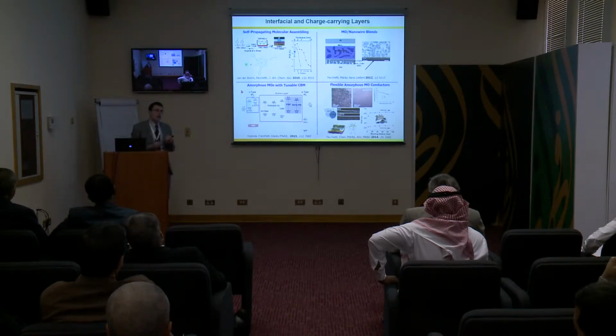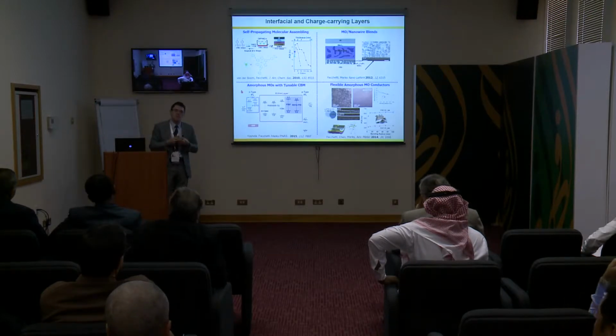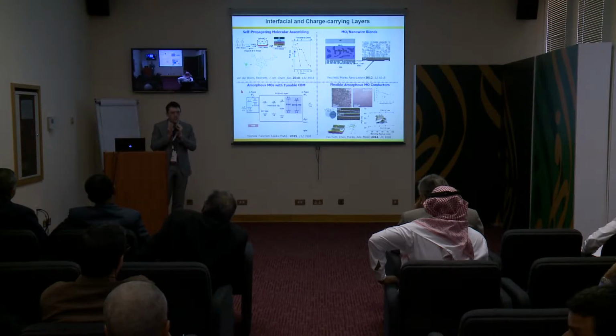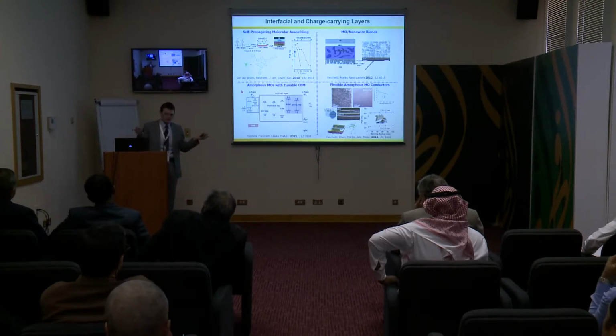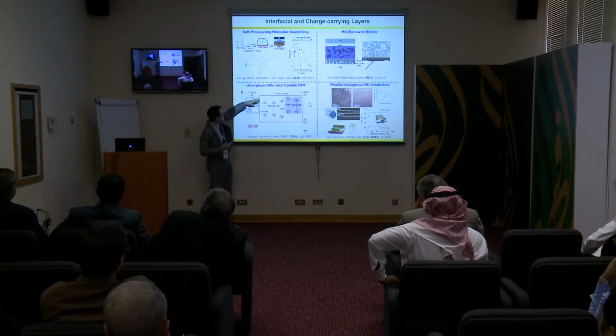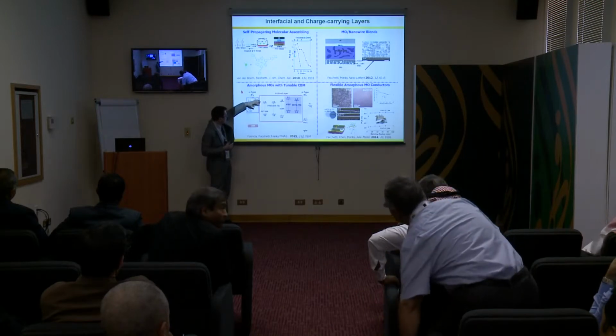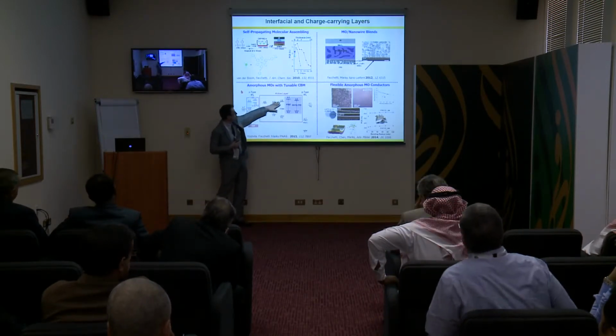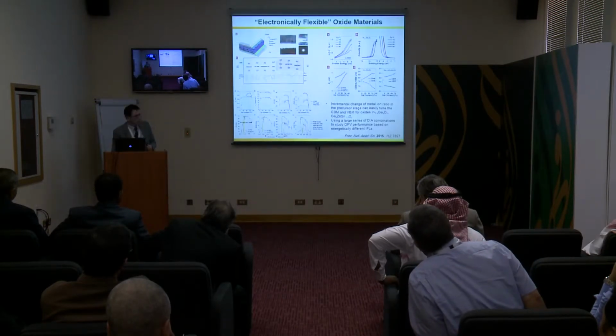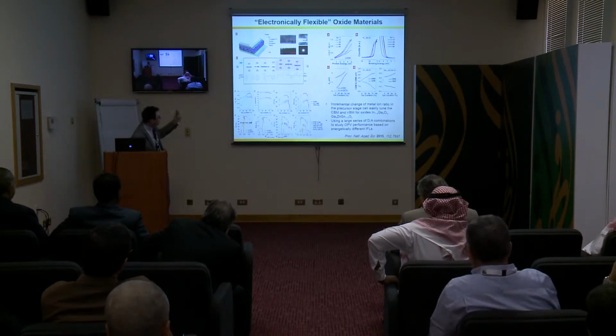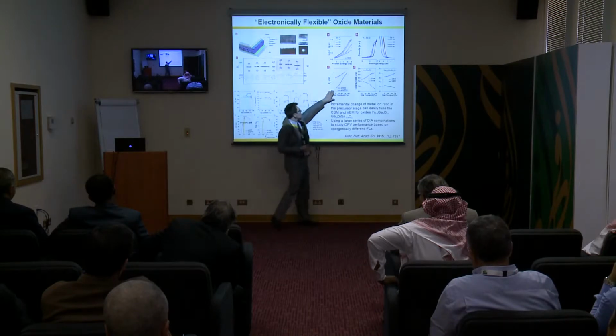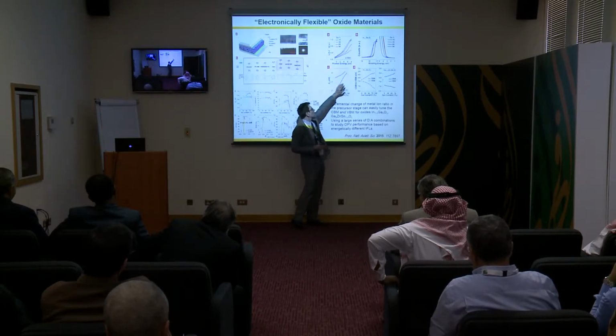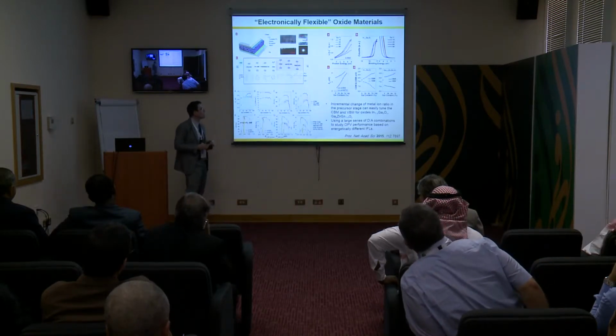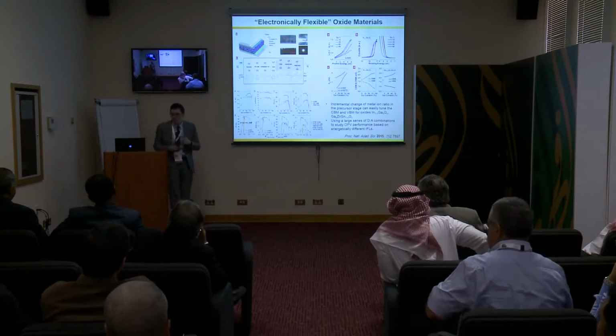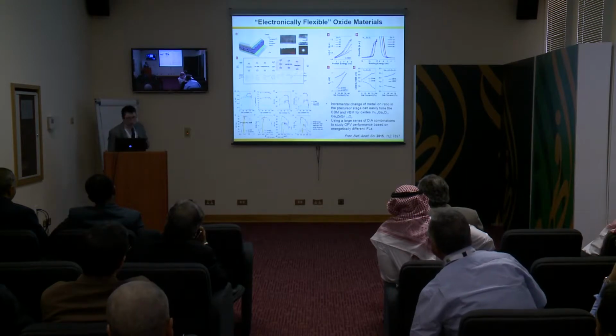This is very important because until a few years back, we only had PCBM as an acceptor. The energetics variation of the acceptor was very, very small, but now we have a much greater variety of acceptors. We have small molecules, we have polymers, so we really need to expand the variation of the energy at this interface to be closer to the variation in the energy of your acceptor. And we have done this again using metal oxide and using doping to change the energetics of these interfaces by quite a large amount. You know, we can go from about 3.5 to about 4.3, 4.4 electron volts. So quite a tuning in the energetics.